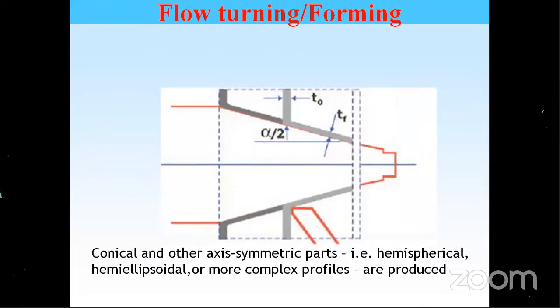Then another important thing actually, how to make a cone. Normal aluminum alloy you can make a cone, but making a cone from a special alloy is very difficult. So we have a new technique called flow forming, which because of my pressure many of the industries, at least I know 3-4 industries, have already invested in and are already making it. When you go home, check your cooking gas cylinder actually. They are flow formed cylinders without any long seam weld.